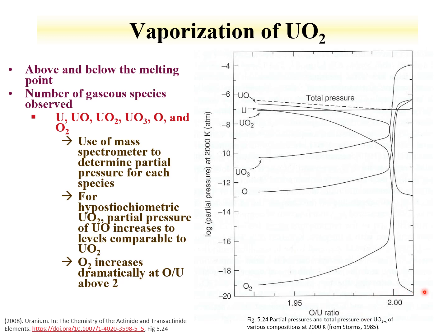And the reason that that's important, if you think about when uranium fissions, the fission products are going to want to form oxides. How much oxygen is available will dictate which fission products can form oxides, and as we'll learn when we evaluate the chemistry of fission products in spent fuel, we'll see that some metals, such as the metals from molybdenum up to palladium, form metallic inclusions. There's not enough oxygen around to oxidize those metals.